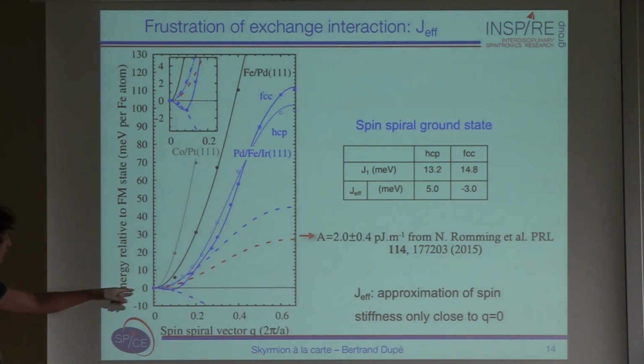But as soon as you have a spin spiral ground state, like here in the FCC case, you actually have a negative J effective, because the dispersion curve has a negative curvature close to the gamma point. So you end up with a system, palladium HCP on iron on iridium 111, where you have a J effective which is positive, not too far from the one obtained from experiments. And for FCC, you have one which is negative, very far from the one obtained from experiments.